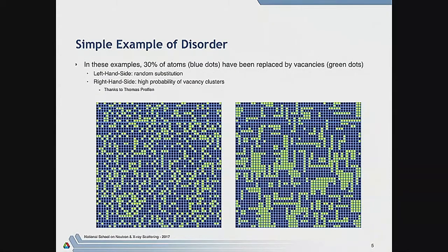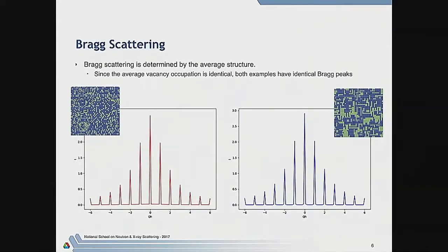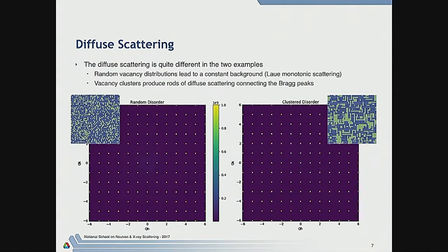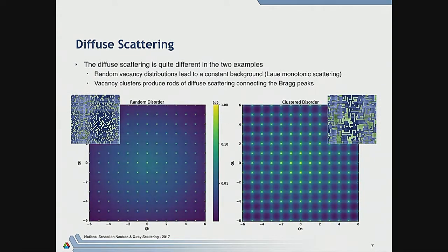Now, why diffuse scattering? In principle, suppose we have two models of disorder, a case of substitutional disorder. On the left, we have an array of two different species of atoms, randomly sited on this square grid. On the right, the yellow atoms have a tendency to cluster together. They give rise to exactly the same Bragg peaks, because the average compositional disorder is the same. Diffraction will just say the average occupation is whatever percentage it is, and that's nearly all you can learn from it. But with diffuse scattering, the Bragg peaks look all the same, yet you see the diffuse scattering is quite different.